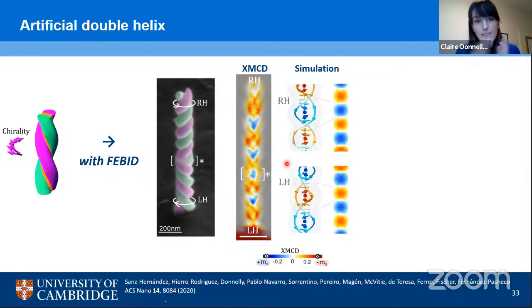Now, this makes sense, I think, because if we think about how the helices are grown, they're grown in parallel. And when they are still very small, we believe that they will be able to reorient themselves in order to minimize their magnetostatic energy and therefore align anti-parallel. And this anti-parallel alignment is therefore retained as it grows up along the length of the nanostructure.